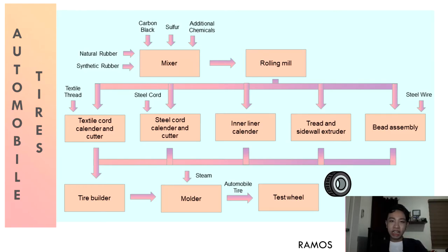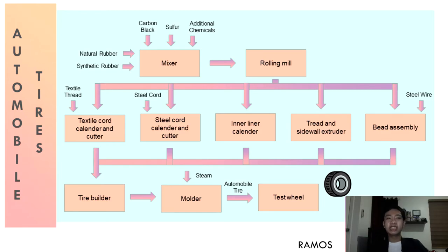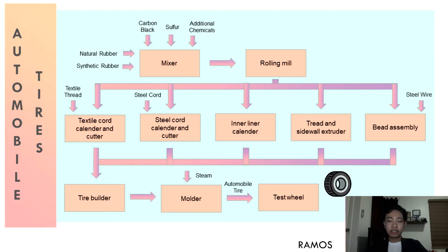Other chemicals are also added to reduce wear and increase the grip of the tire. During mixing, heat is applied to soften the rubber and evenly distribute the chemicals. The temperature during mixing is 160 to 170 degrees Celsius during the first stage and 100 to 110 degrees Celsius during the final stage. If the temperature is too high, the rubber compound may be damaged. After mixing, the product goes through a rolling mill that squeezes it into thick sheets of rubber.